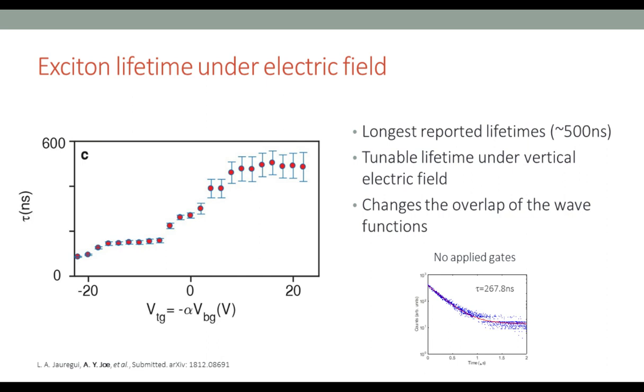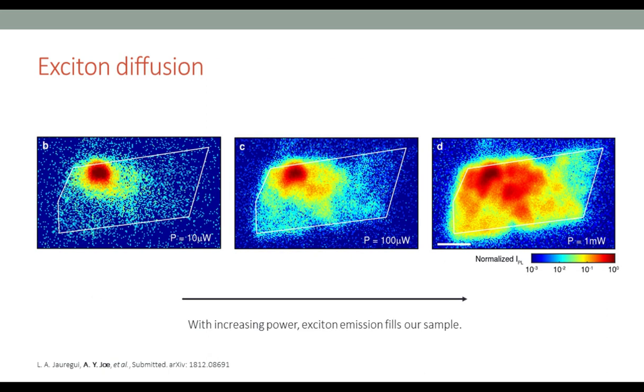It's also quite interesting that the electric field can tune the wave function overlap. In order to see diffusion, we need permanent dipoles, which we saw with the electric field, and we need the long lifetime, which we observed here. So we now tried to do these diffusion measurements. What we did is excite in one corner of the sample. If you look at the far left panel, we excite in one corner of the sample at 10 microwatts, and then collect PL emission, just counts from all across our sample.